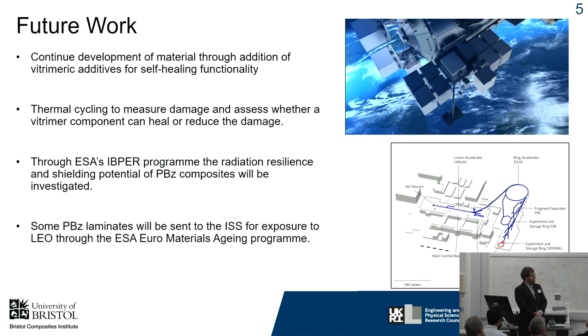And then, current and future work: what I'm currently working on is attempting to add some vitrimeric additives into the polymer system, which will hopefully add a bit of self-healing functionality, which we would test by thermal cycling, possibly some ballistic testing, and then compression, either with or without heating, which might be able to trigger the healing effects of the vitrimers.